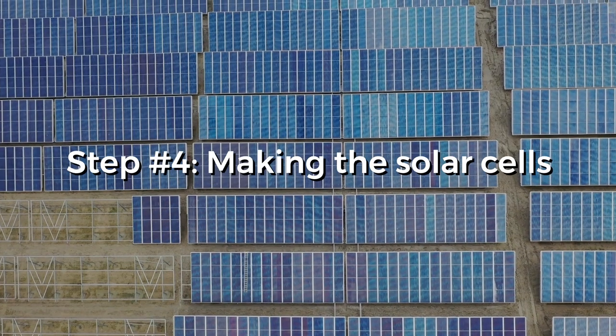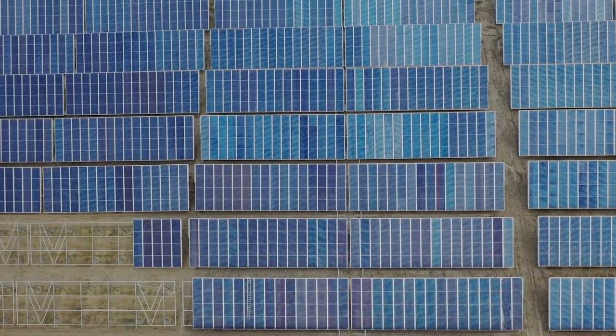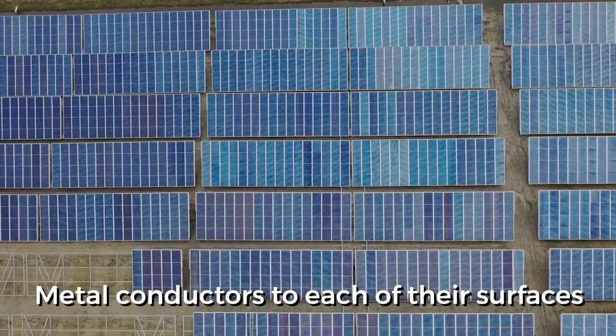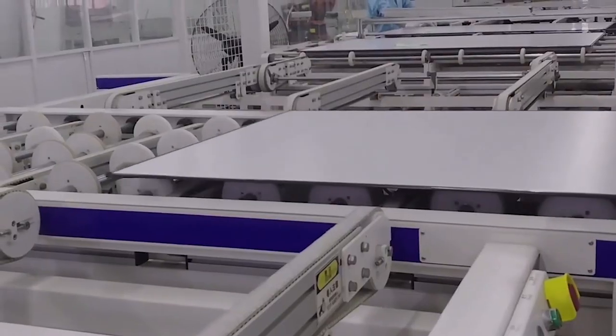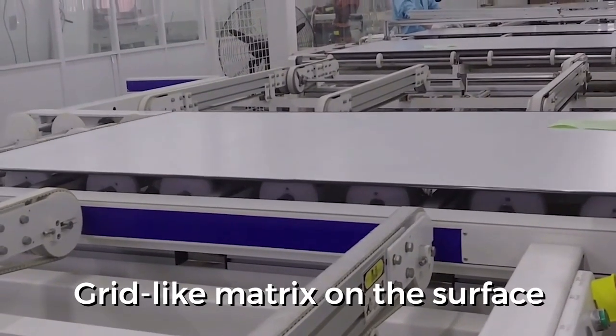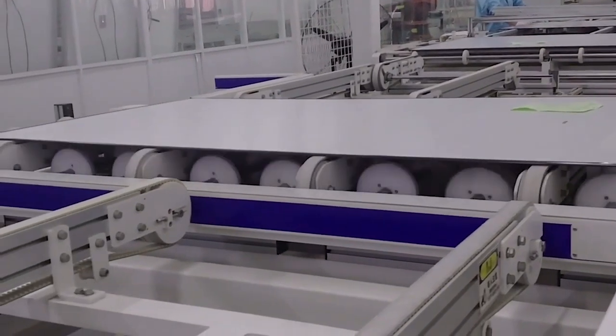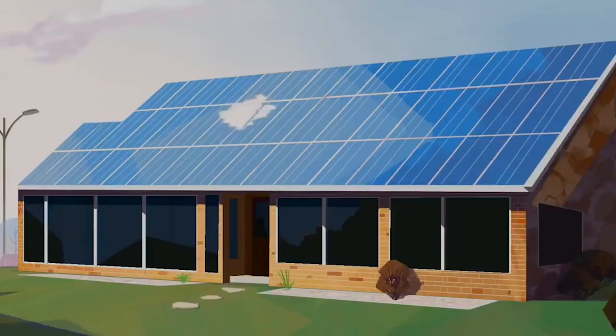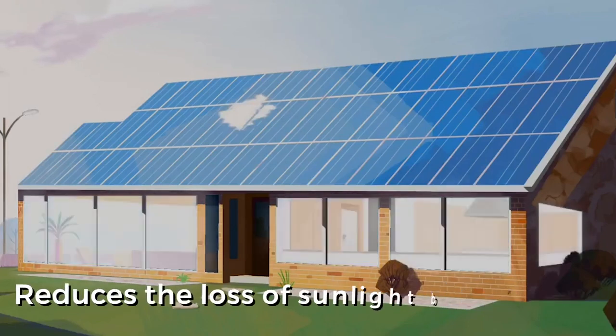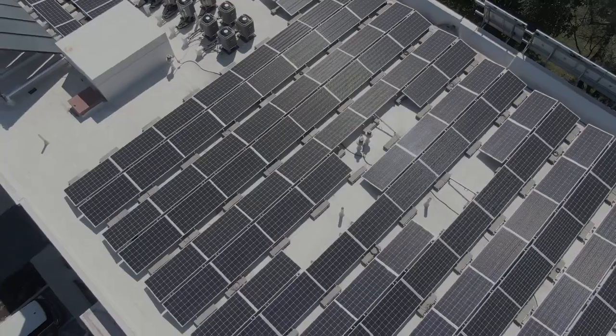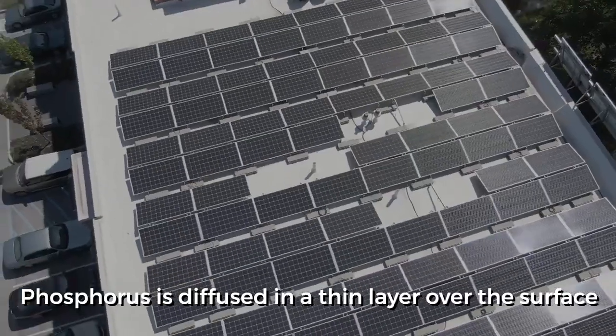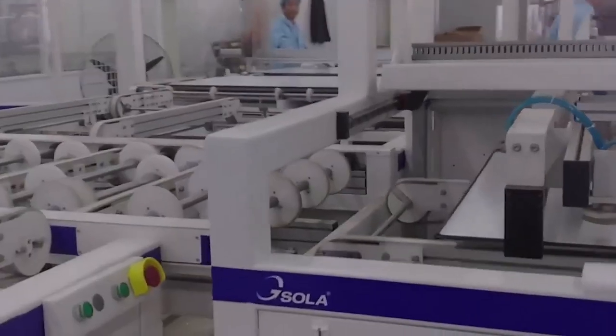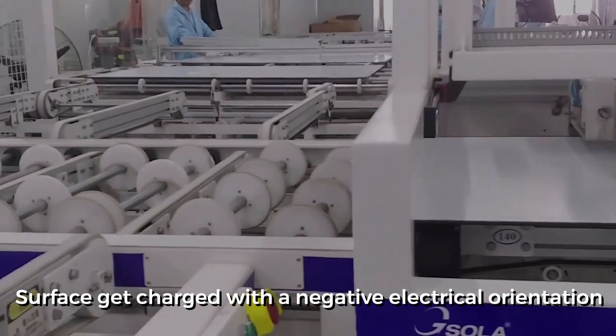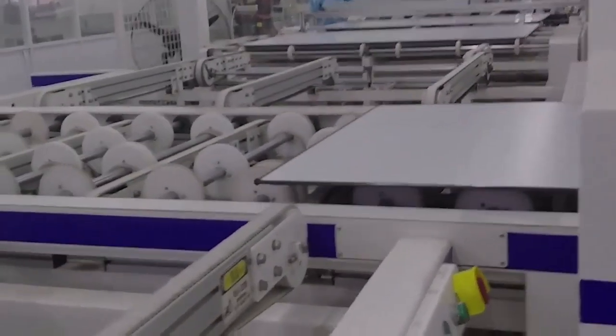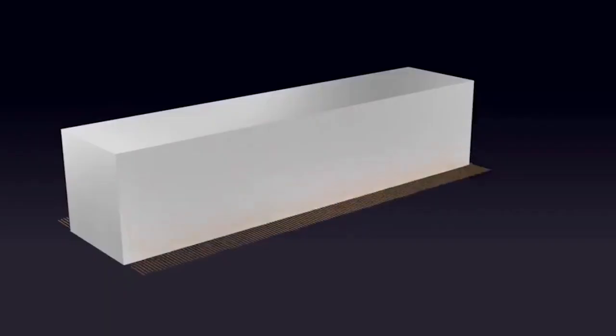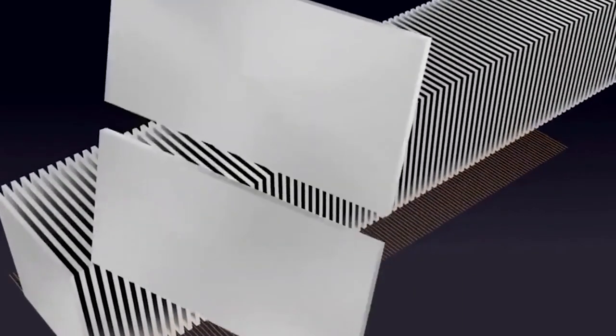Step 4. Making the solar cells. The wafers are converted into solar cells by individually treating them by adding metal conductors to each of their surfaces. Due to this, the wafers get the characteristic grid-like matrix on the surface. This helps in the conversion of solar energy into electricity. Also, the coating increases the absorption of sunlight and reduces the loss of sunlight by reflection. Even phosphorus is diffused in a thin layer over the surface of the wafers inside an oven-like chamber, and this makes the surface get charged with a negative electrical orientation. The use of boron and phosphorus leads to the incorporation of a positive-negative junction, which is important for the functioning of the solar cell.